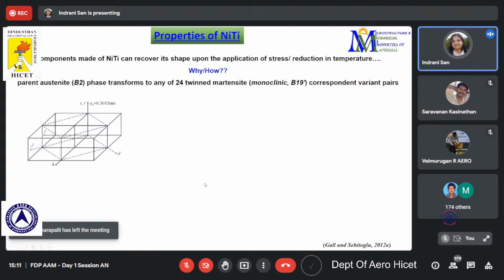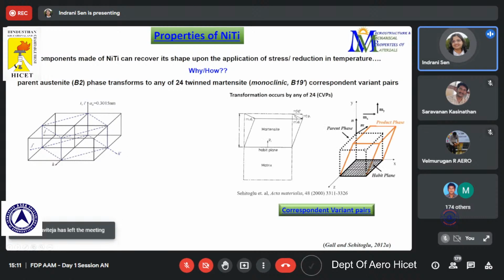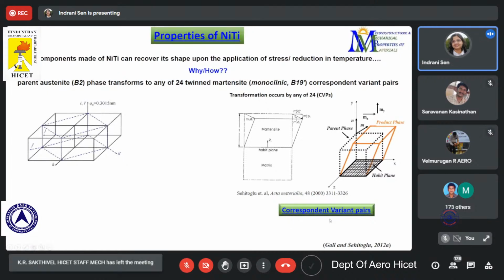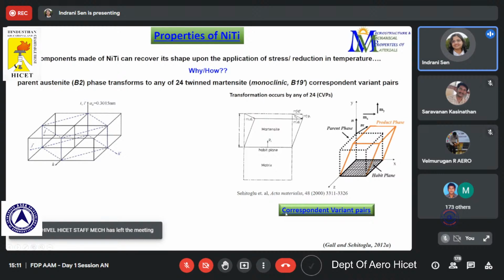So far so good. But how is this conversion happening? You see that when a cubic structure, the dashed one here, and the orange one is the martensite structure, when this parent phase, the cubic phase, converts to martensite, it can happen along different variants. And in case of nickel titanium, there are 24 different correspondent variant pairs. So this transformation can happen through any one correspondent variant pair. Just one out of 24 will be selected, and this selection is done based on the energy criteria.